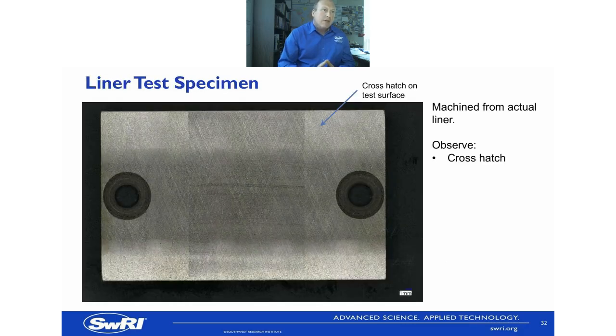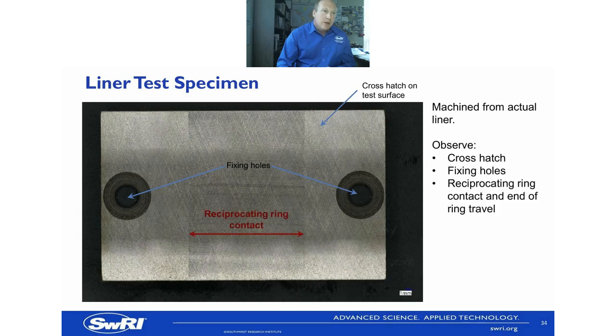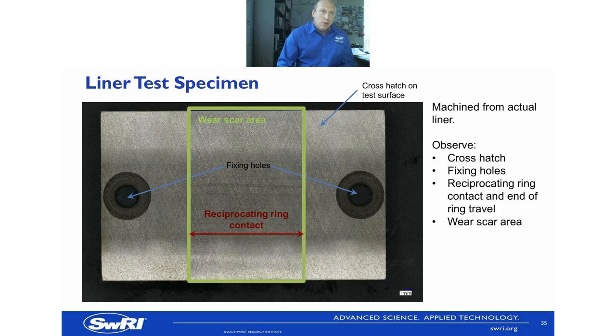What we're going to look at is the liner specimens. So note, if you look closely, you can see the crosshatch on the test surface there. These are just the fixing holes that we screw down to the base of the T77 to hold it in place while we're doing the testing. This is the reciprocating ring contact. So the ring is reciprocating backwards and forwards on that area. And this is the wear scar area that we're going to be looking at. So that's what you want to be focusing on the next few slides.